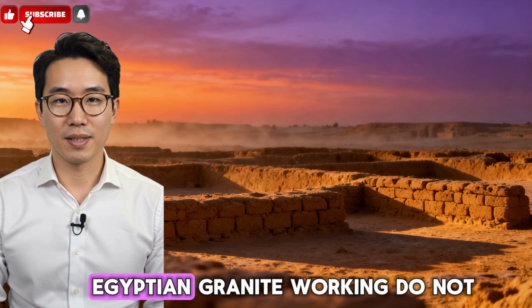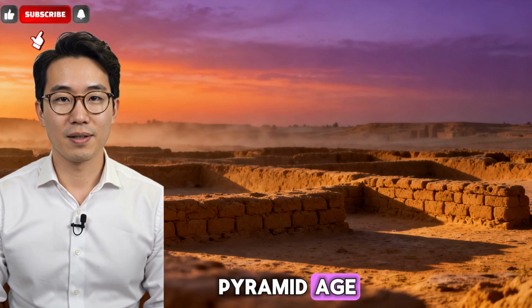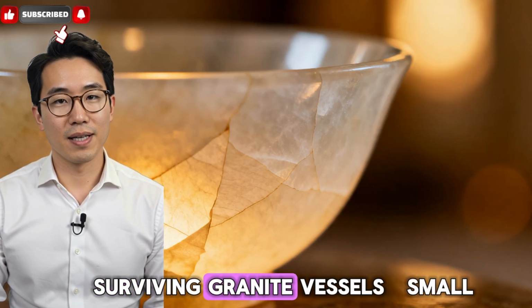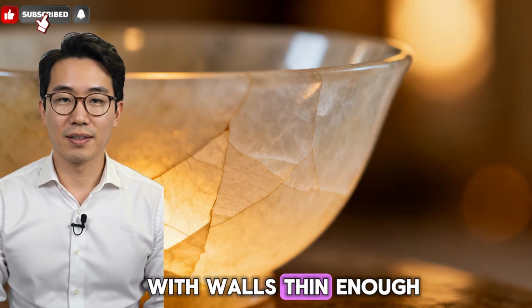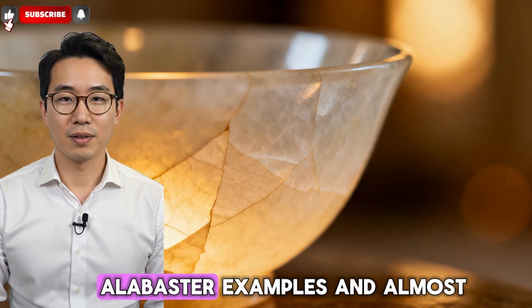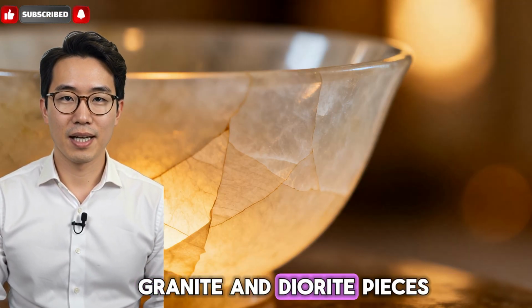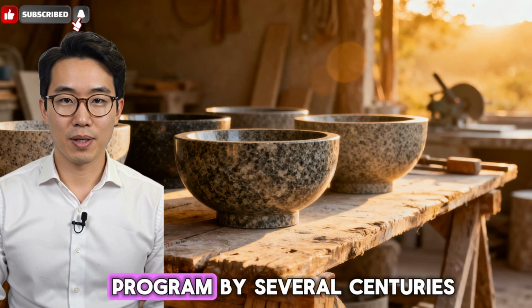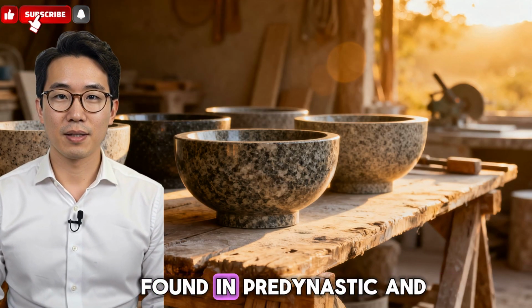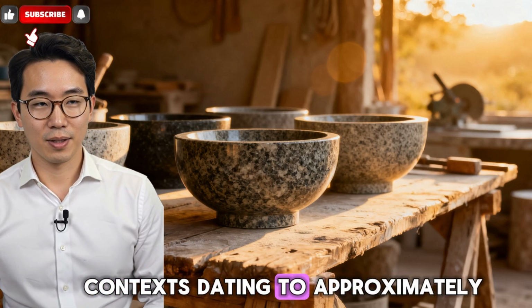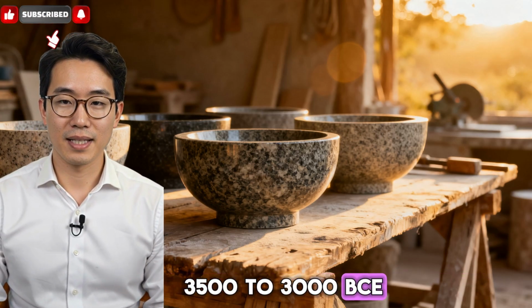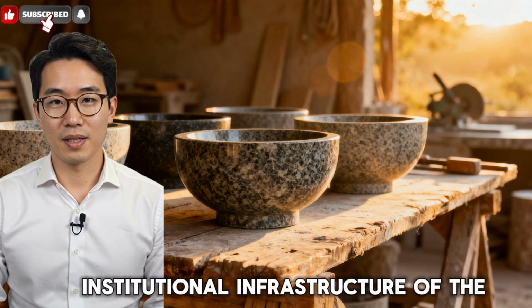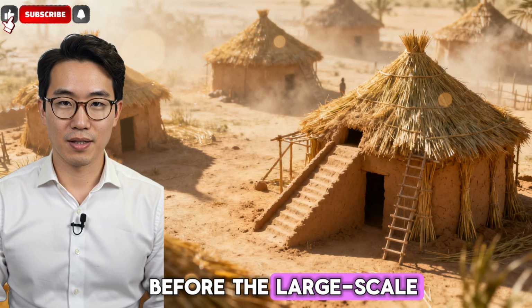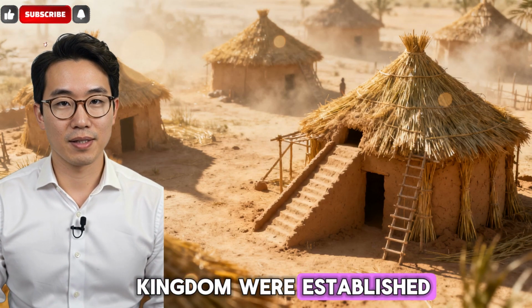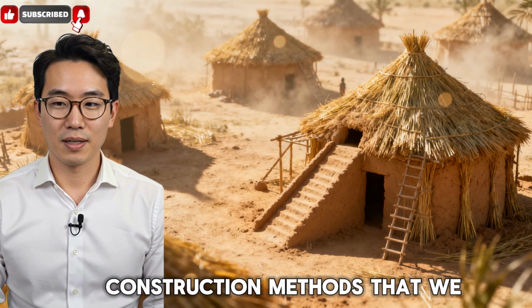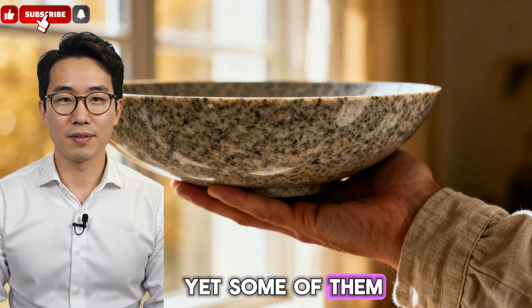The most puzzling examples of Egyptian granite working do not all come from the Pyramid Age. Some of the most technically challenging surviving granite vessels, small, hollow containers with walls thin enough to be translucent in the case of the finest alabaster examples, and almost as thin in the hardest granite and diorite pieces, predate the Old Kingdom pyramid building program by several centuries. These vessels, found in pre-dynastic and early dynastic contexts dating to approximately 3500 to 3000 BCE, were produced before the institutional infrastructure of the pyramid building state existed, before the large-scale organized craft workshops of the Old Kingdom were established, and before any of the documentary evidence of construction methods that we have for the pyramid period. Yet some of them are extraordinary.